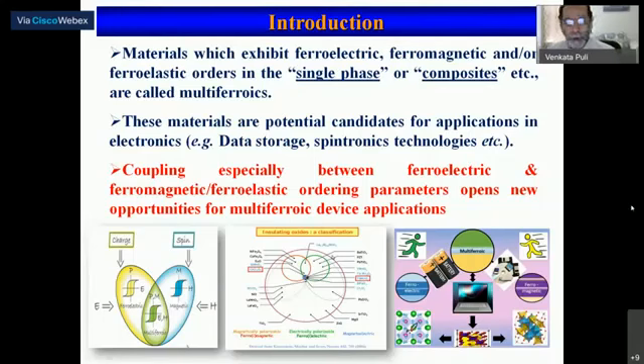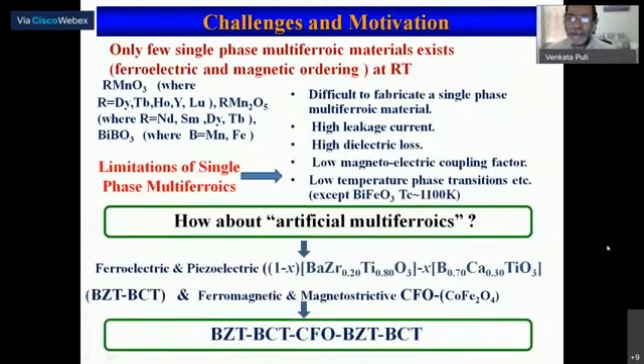We have a very small number of single phase materials for these applications. So we thought of combining different ferroelectric and ferromagnetic materials to obtain multiferroicity. However, there are a few challenges with single phase multiferroic materials. Only a few exist, and the most explored is bismuth ferrite, which has a TC of 1100 Kelvin. But there are difficulties in fabricating single phase multiferroics because of high leakage current behavior, high dielectric losses, low magnetoelectric coupling factors, and low temperature phase transitions. So then we thought of going for artificial multiferroics.